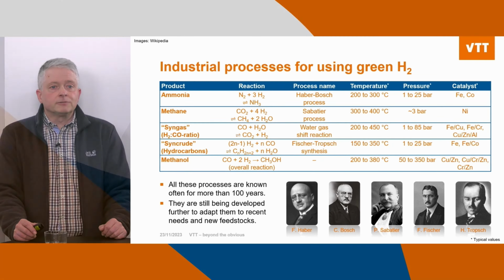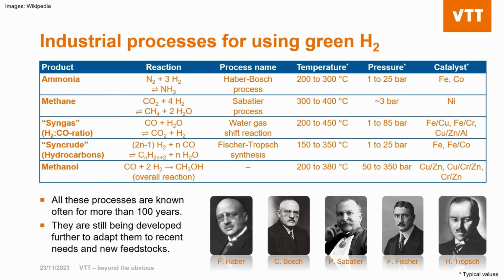When we're looking at these industrial processes where we will use green hydrogen, there are these processes, for instance, for ammonia, methane, and also these hydrocarbons and also methanol. That's possible to do at increased temperature with an increased pressure, commonly using a catalyst. The temperature range is usually about 150 to 450 degrees Celsius, and the pressure can be even several hundred bars if needed.